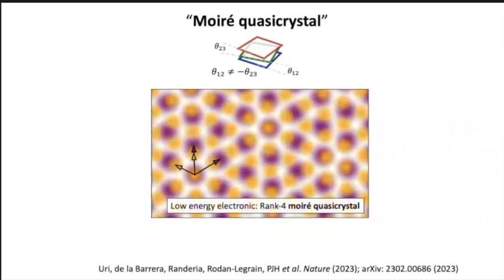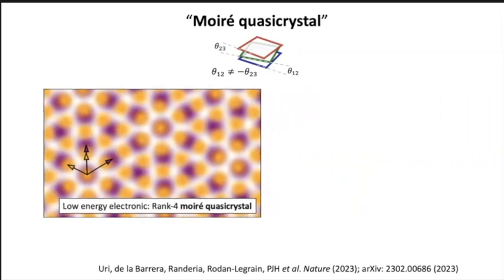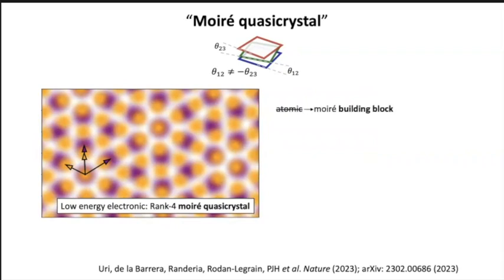So we're going to form a Moiré quasi-crystal, where the quasi-crystallinity is in the Moiré pattern, not in the atomic scale lattice, okay? So this will be a rank 4 Moiré quasi-crystal because it is composed of two periodic Moiré crystals, but which are rotated with respect to each other, okay? And of course, the nice thing is that we can choose now the Moiré as the building block rather than the atomic structure. We can engineer this in various ways, because we have a lot of flexibility with how we choose these Moiré patterns.